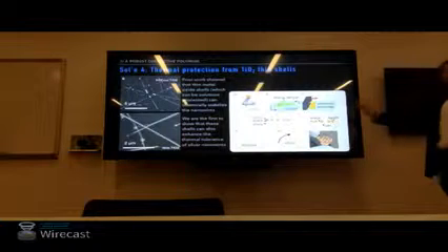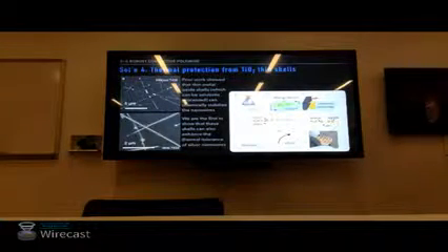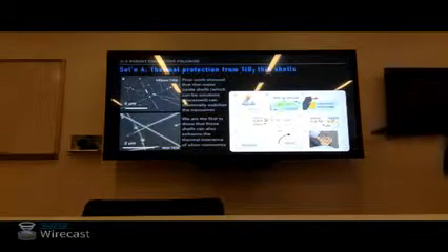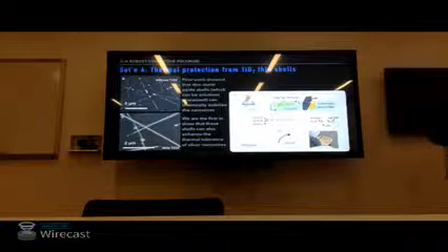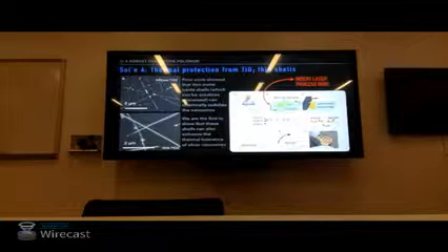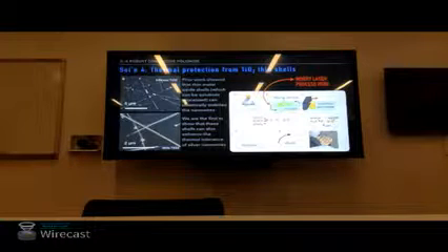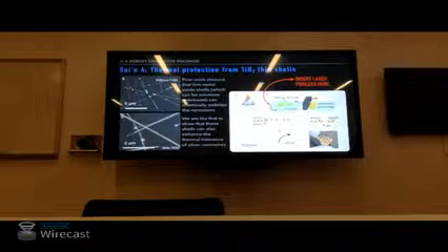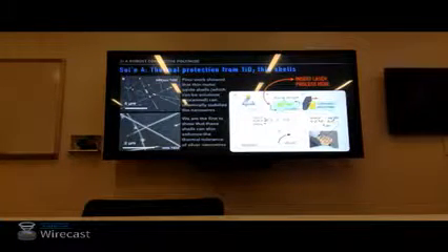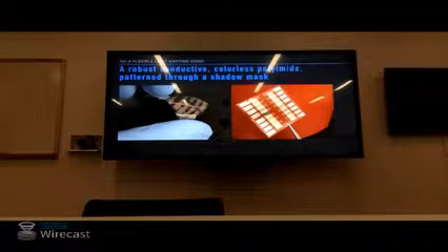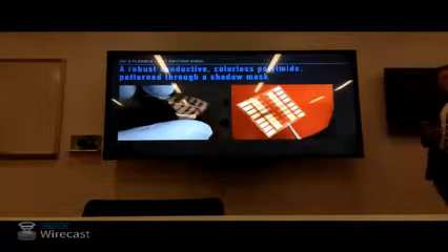We're going to spray coat our nanowires, titania sol-gel, add our colorless polyimide in solution phase. Then we're going to do our imidization, our high temperature cure, lift it off, and we can create patterns by using a shadow mask. We can insert our laser process right there, and what's nice about inserting the laser process at that point is we know how to process nanowires on glass like the back of our hand, right? It's the first thing we did in 2012. It's our bread and butter. We don't have to worry about any of the other materials when we do the laser process. That's a win for us. And what we get are these robust, conductive, colorless polyimides.